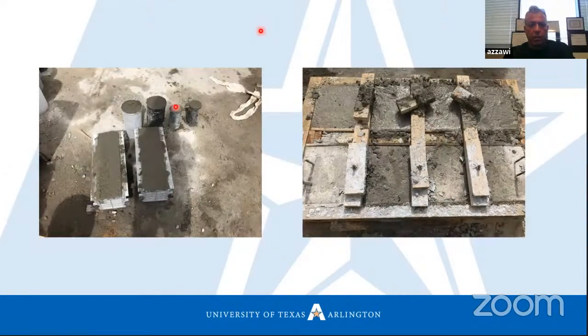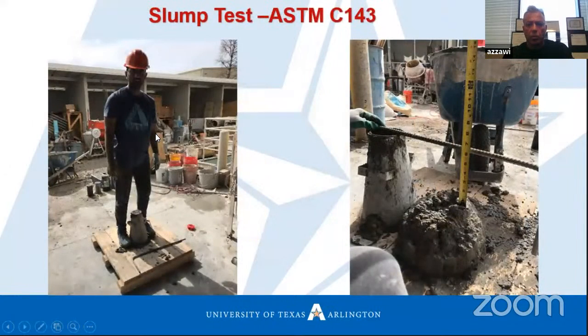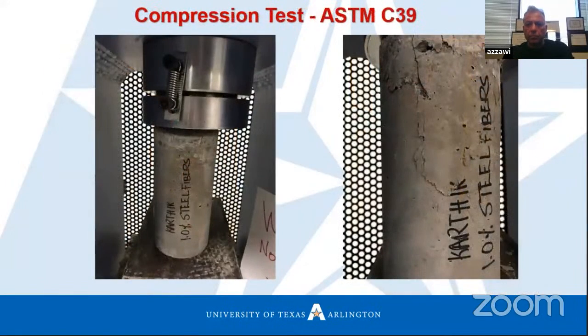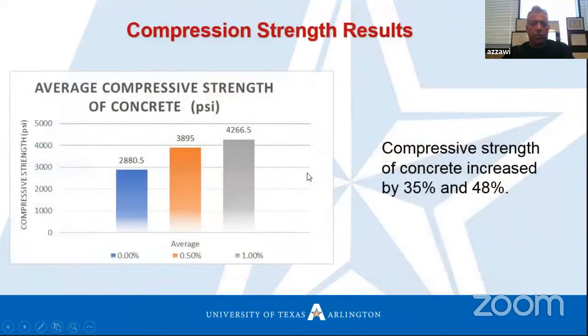This is for split tensile. This is for compression test, and these are for modulus of rupture. Check the slump also based on the ASTM C143. Then we start curing in the curing room. After 28 days, we start testing these samples for compression test, and this is the result for compression test.